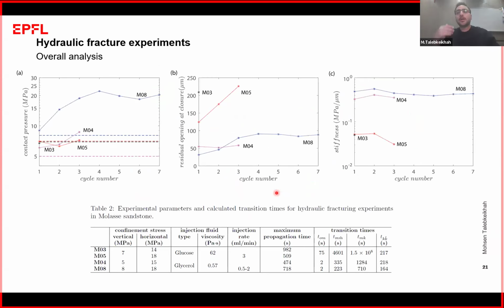So overall, if I want to compare all the experiments, in M08 and M04 we injected glycerol, and in M03 and M05 we injected glucose with higher viscosity. At first, let me show you this figure. These are the peaking contact pressures for each cycle. You can see that for both M08 and M04, where we were using lower viscosity fluid, the peaking pressure points are higher than the vertical confinement stress in those experiments. However, in M03 and M05, the contact pressure for that peaking point is around that value, and in some cycles a bit higher than the vertical confinement stress that we have.